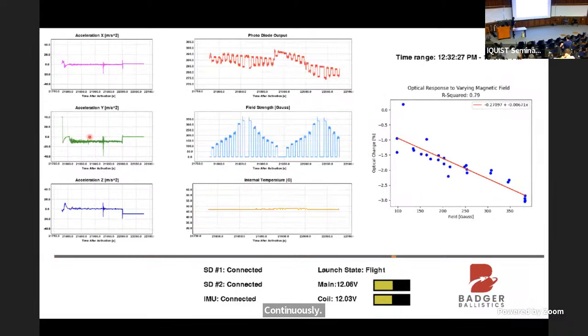And then this is the zoom in of the data during the flight, where all these steps of the photodiode are basically when we turn the coils on and off. And during this time, we can collect data on the optical change as a function of the applied field. It shows the same slope as during the rest of the sequence, showing that our sensor remains functional this whole time. So this was our first experience in packaging this type of all-optical sensor.